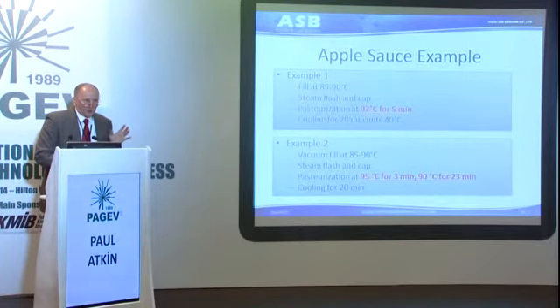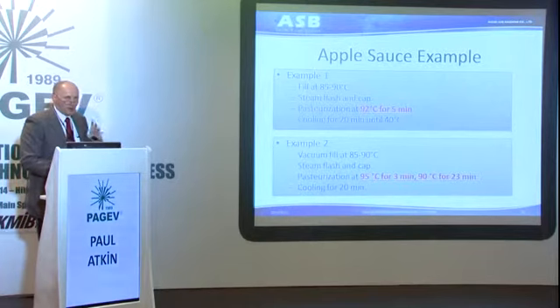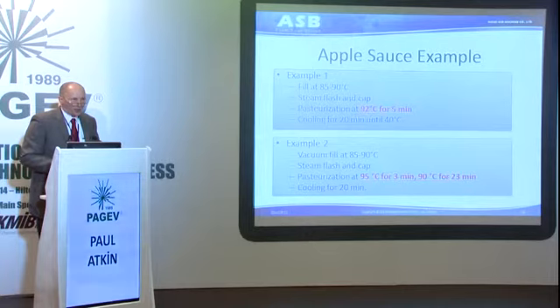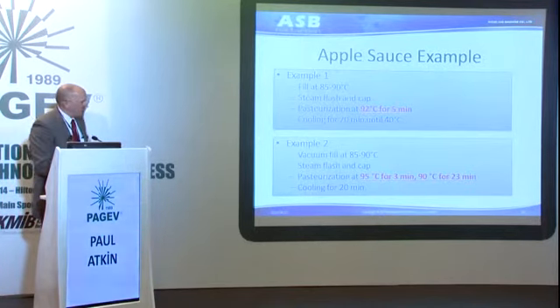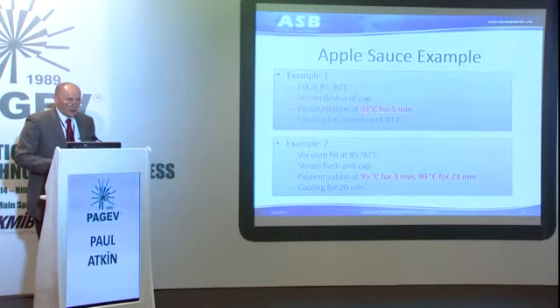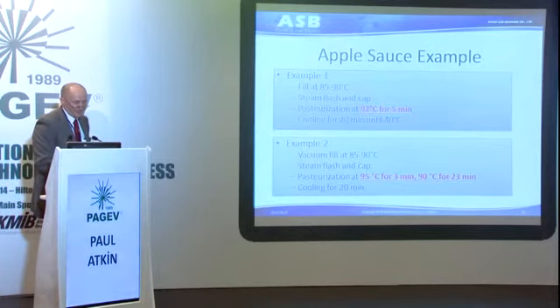Just to show some examples, this is an apple sauce. Both are apple sauce, both are in Japan. Just the difference is 2 different companies. And one company is providing pasteurization at 92 degrees C for 5 minutes. The second example, 95 degrees C for 3 minutes, then an additional 90 degrees C for 23 minutes before cooling. So same product, but a very diverse set of filling characteristics.